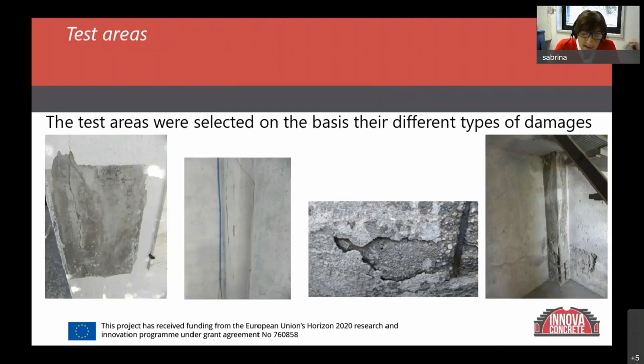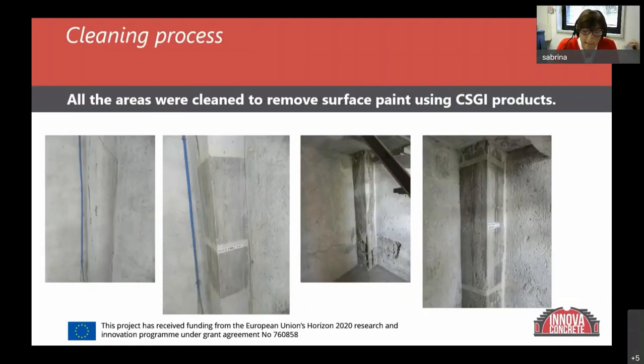The areas for the experimental tests were selected considering the characteristic of the cementitious mortars, the level of degradation, and the type of the product to be applied. We selected the areas with different level of decay to verify the efficiency of the new products under different conditions and inside and outside the monument. As foreseen, before applying the products, the selected area were cleaned by removing the superficial paint layer present on the walls.